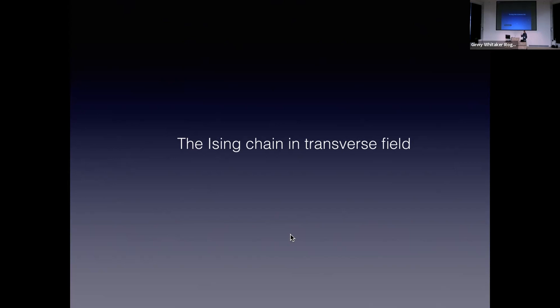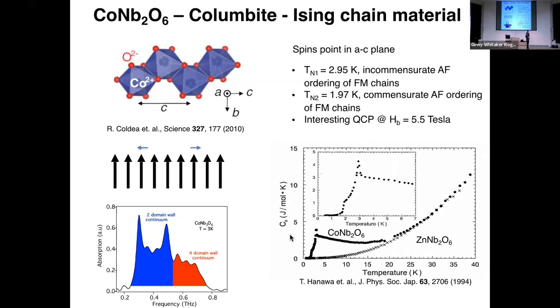I'm going to talk more about hexagonal magnets and the realization of a quantum spin liquid, but I'll get there in a roundabout fashion. Let me first take a diversion through a cobalt material — cobalt niobate, CoNb2O6 — a material I've been interested in for a long time. It was pointed out by Radu Coldea, now over 10 years ago, that this quasi-1D zigzag chain cobalt material has strongly bond-dependent Ising interactions and is the best material realization of a 1D Ising chain tunable through a quantum critical point with a transverse magnetic field.